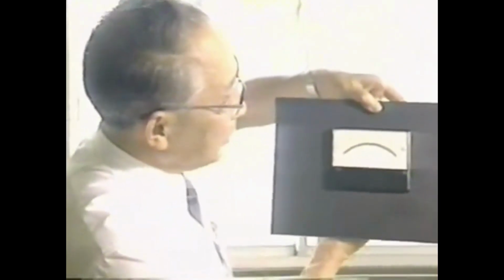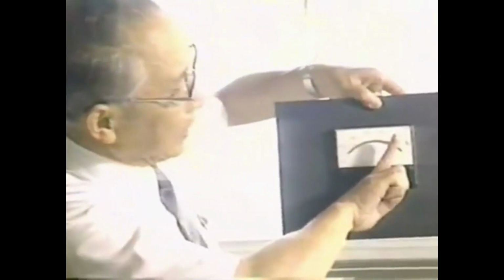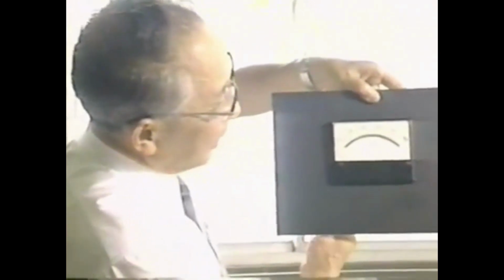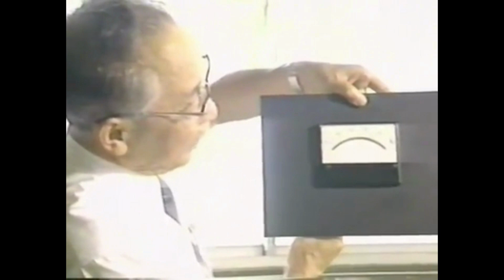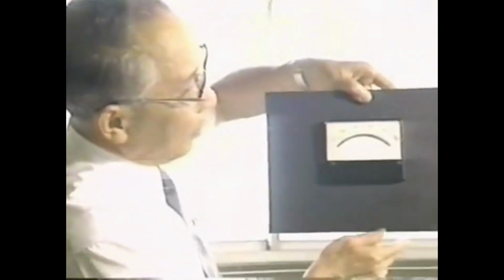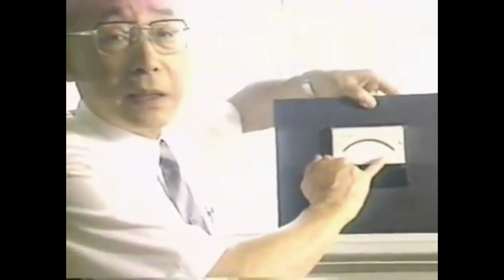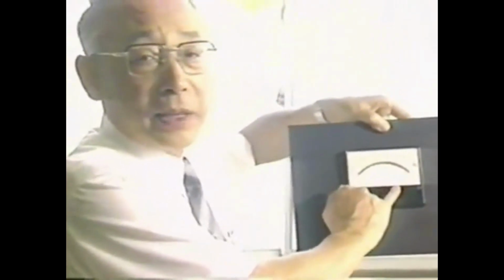We were unable to buy advanced American equipment. The temperature gauges at that time were rounder and bigger than this and had a large needle. When we raised the temperature, this needle shot right up to 600 degrees, then 800 degrees, passing the melting point of germanium until it arrived at approximately 1,000 degrees centigrade. At that point, we lowered the temperature slightly. But as you can note, this needle mainly measures units of 1 degree, and 0.1 degree can't be seen. For that reason, no matter how many times you try, you'll fail at making crystals.